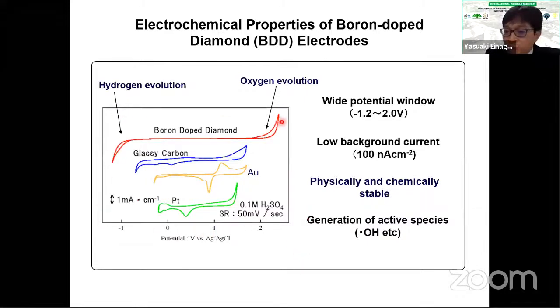Most of you probably know the electrochemistry well, I hope. For conventional electrodes such as glassy carbon, gold, and platinum, when we apply one point several volts, oxygen evolution starts. On the other hand, when we apply a negative potential like minus 0 point several volts, hydrogen evolution starts. So this is the potential window. When we use the boron-doped diamond electrode, oxygen evolution starts at a very high potential, and hydrogen evolution is also difficult to occur. So this is a very good property: a wide potential window.